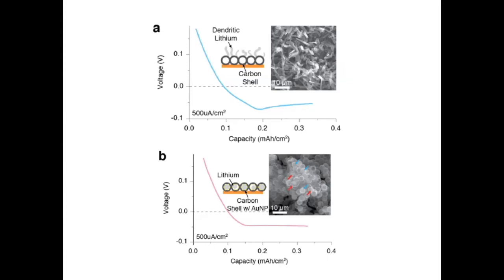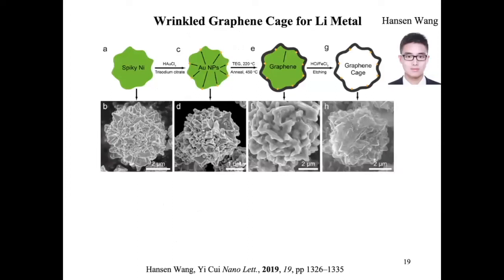So with the gold seed and this hollow carbon at the bottom, we see after deposition of a certain capacity, you don't see lithium filaments growing out, but in the top hollow carbon case without gold seed, you see lithium metal deposition outside. Very clear difference. If you look at the battery Coulombic efficiency, the top is very low. The bottom is a lot better. This is back in 2016. Then we asked the question, what type of carbon would be the best?